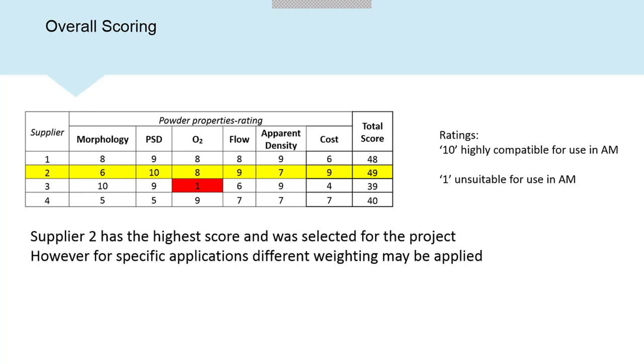So not all of these suppliers were European-based. Some suppliers would have scored higher because of the fact that we're European-based rather than other areas of the world. So generally speaking, once you've got multiple suppliers, you want to specify against both technical, so that's all the properties, but also the commercial. In this case, supplier 2 was selected as the preferred supplier to the AMAZE program, and we continued to work with supplier 2 for the duration of the project.